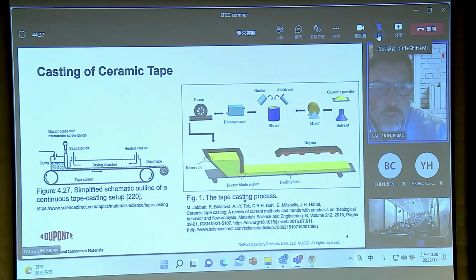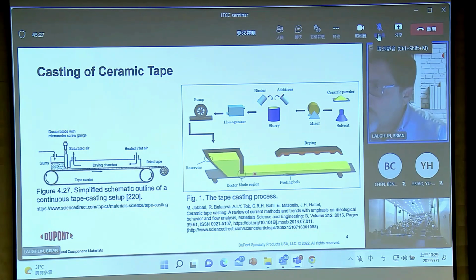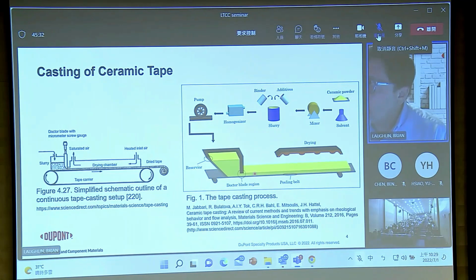The process that we internally provide to the industry is a ceramic tape. Here are some references and figures for how you make this unfired ceramic tape. We start with our proprietary recipes and raw ingredients of ceramic powders, mix them with solvents, add binders and additives, make sure everything has high quality, and then put it in a doctor blading or slot coating type apparatus that pulls a mylar film under the wet slurry. The cast material on the mylar film then has the majority of the solvent driven off, to leave a flexible piece of laminate material that has all of the ceramic precursors as well as some binder resin that keeps everything together. That we provide in the process that we run prior to it being sold out in the industry.